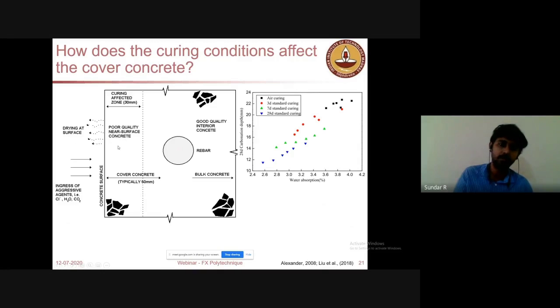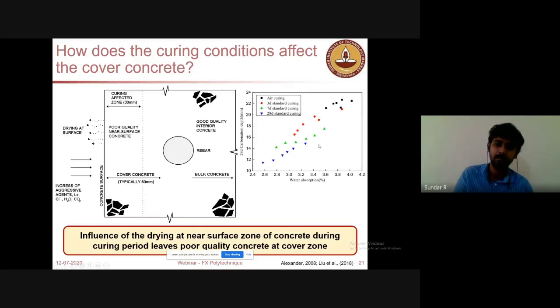So there is a chance of having poorly compacted, loose concrete here. So curing has become of prime importance in concrete. If you see here, this is a set of concretes. When it is cured without any curing, you could see there is a very high carbonation depth at a given time of testing.